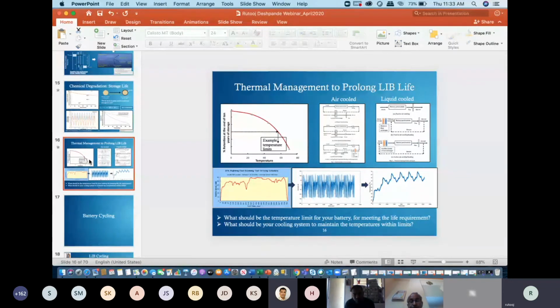Yes. What is the effect of low temperature on a battery which is discharged to 20 percent or lower? Can it deliver the same energy when it is fully charged again? Yeah. If you just cool down the battery to, let's say, 0 degrees Celsius, or minus 20s, minus 30s, and you do not do anything, if you are not using the battery at those temperatures and you just bring the temperature back to 25, lithium ion cells would not have any effect at all, or have very minimal effects.